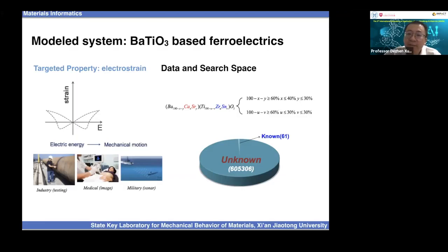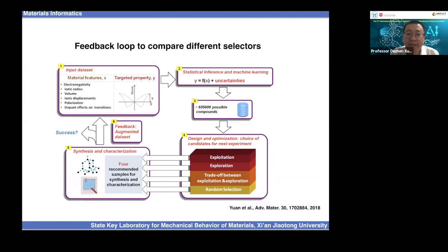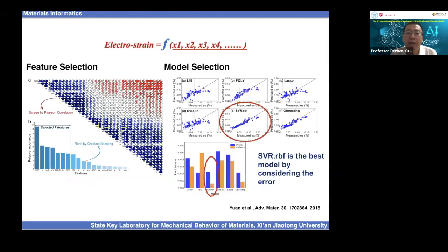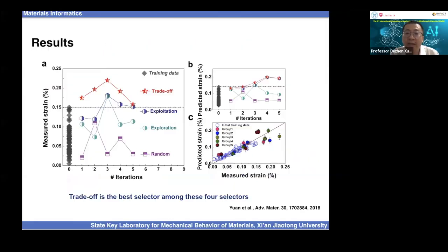So the data and the search space is, we have 61 known data. So these 61 data, we have real properties. We build the model on these 61 data points and to search for the new material in these 600,000 possibilities. So we use the design loop, and we use different selectors to choose different experiments, and we see which selector chooses the best material. And we build the machine learning model, and we do the feature selection, we do the model selection, and we find the SVR-RBF is the best model, and it can give us the prediction.